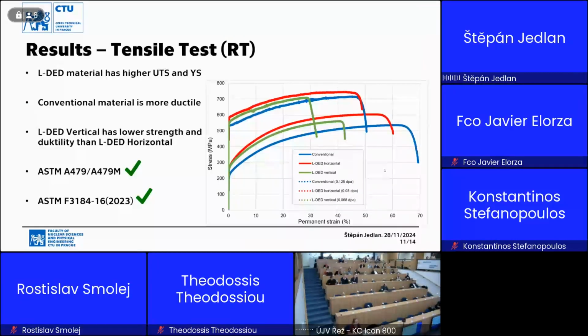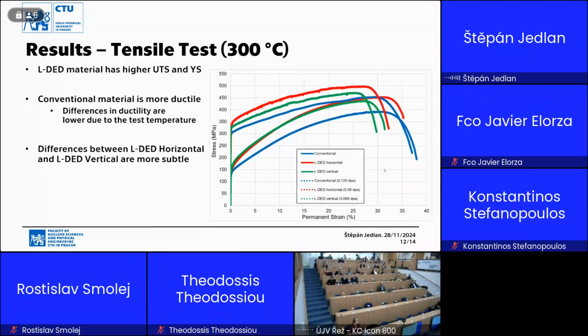as a result of the heat treatment, which I will be talking about soon, the LDED vertical and horizontal printed material had the highest strength, but a little bit lower ductility. And for these 300 degrees Celsius tests, the results say that the differences between the 3D printed material and the conventional material are more subtle, which is due to the higher test temperature, but still the results are almost the same in that the 3D printed material has higher strength but lower ductility.